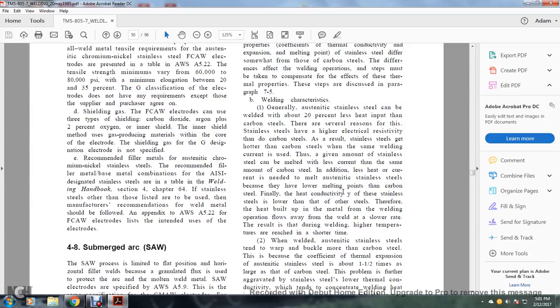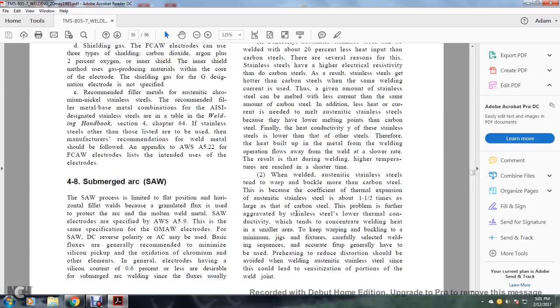Also, the heat conductivity of stainless steel is lower than that of other steels. Therefore, heat built up in the metal from the welding operation flows away from the weld at a slower rate, with the result that during welding higher temperatures are reached in a shorter time. When welded, austenitic stainless steel warps and buckles more than carbon steel. This is because the coefficient of thermal expansion for austenitic stainless steel is about 1.5 times that of carbon steel. The problem is further aggravated by the stainless steel's lower thermal conductivity, which tends to concentrate welding heat in a small area.